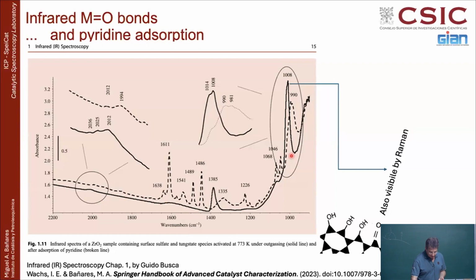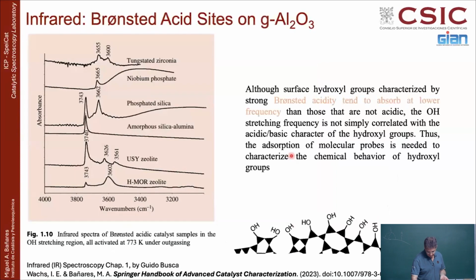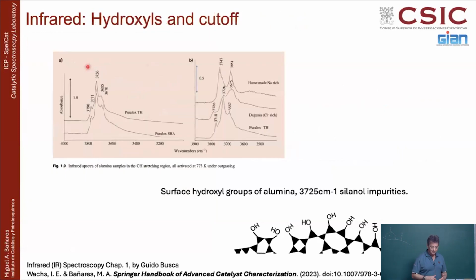So depending on whether the pyridine binds, it will result in, sorry, that one was misplaced, but anyhow, I will go back to that in a moment. Before going to the pyridine, just looking at the infrared position of the hydroxyl groups, you can tell how acidic it is, because the more Brønsted acid the hydroxyl group is, the lower the frequency it is. So here you have hydroxyls in a mordenite zeolite, in ultra-stable Y zeolite, on amorphous silica. So you see how these zeolites have more acidity than the amorphous silica. Or a phosphated silica because of the phosphate group, or the niobium phosphate, which is acidic, or tungstated zirconia, which is acidic. You see how they go to lower frequency.